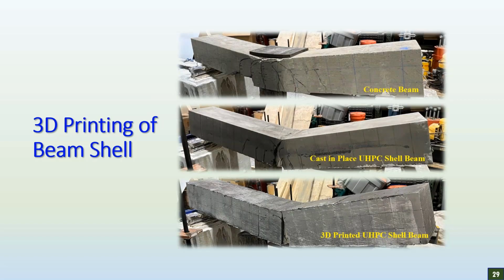These are the tested specimens. All three are shown. On the top, the concrete beam, and you can see that there are quite distributed cracks in it. In the middle, the cast in place specimen is shown, and it has one large crack in the middle on the UHPC shell. At the bottom, the 3D printed UHPC shell beam is shown. And again, you can see that the behavior of both the cast in place specimen and the 3D printed specimen is quite similar in terms of cracks. They both had one large crack in the middle.